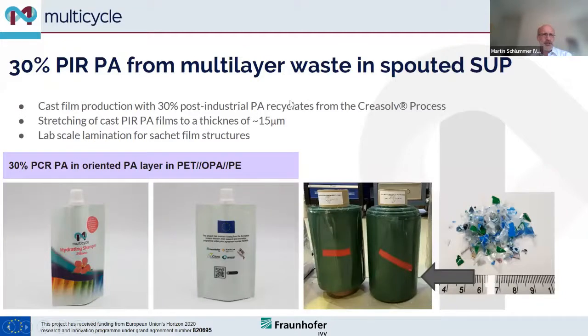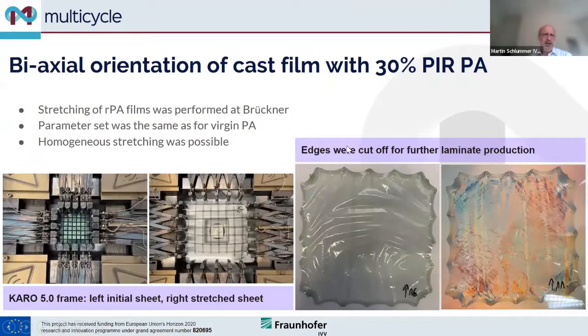It was also possible to make use of the PA, which was left over from the multi-layer fractions. This PA was also purified in the Creasolv® process and was used here in these cast films with 30% of the PA fractions, and it was then used for these very nice demonstrators made from PET, oriented PA and PE. And for the film experts in here, it was even possible to make a biaxially oriented cast film with 30% of post-industrial PA. Here you see the stretching behavior. It was really homogeneously stretched, and the leftovers here were used for the other project up there. So, wonderful outcomes in the packaging area.